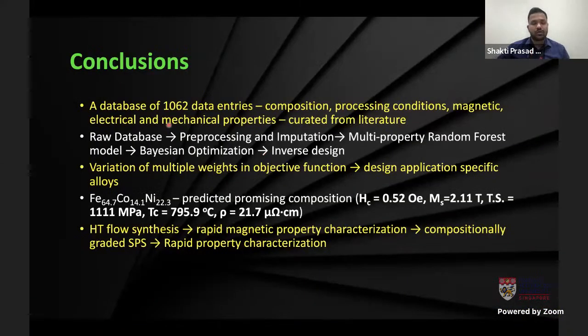So to conclude, basically we had 1062 data entries in the database. Then we had a raw database, which is pre-processed and imputed, and a random forest model was developed with Bayesian optimization, and inverse design was done. Variation of multiple weights in the objective function was also explored to design for various applications. And then finally a promising composition was predicted, which is iron 64.7, cobalt 14.1, and nickel 22.3.